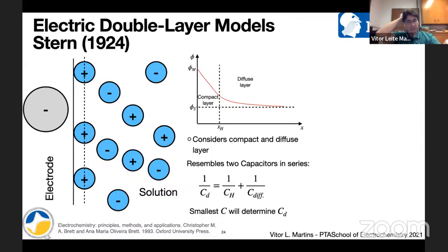So what this tells us is that the capacity or the capacitance of this double layer resembles the sum of two capacitors, because you have the capacitance of the compact layer and the capacitance of the diffuse layer. So we know that for two capacitors in series, we obey an equation like that. So it's the sum of the inverse, the reciprocal, of the capacitance of each layer, right? And in an equation like that, you know that the total capacitance, or the double layer capacitance, will be determined by the smallest one. So the smallest value here will dominate the total value, right?